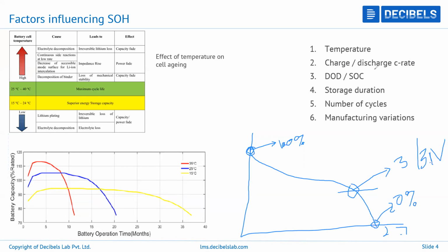So always maintain a responsible, or you can say a sensible, DOD. We should never go 0 to 100, 100 to 0. This will give very less cycle life, somewhere around 500 to about 800 cycles if you're going for full DOD. But this can give way more, from 1200 cycles to about 1500 cycles, if you're keeping the DOD within, say, 85% to about 25 to 20%, right? If you stay within this, your number of cycles and your shelf life will increase. So this is the effect of depth of discharge on the cycle life, that is to say the state of health.